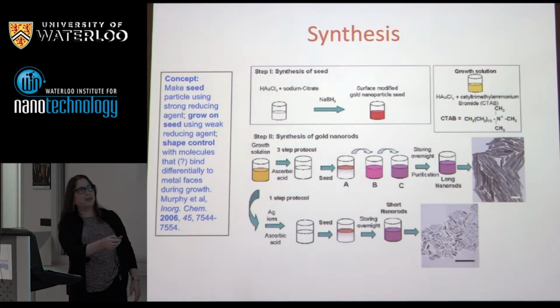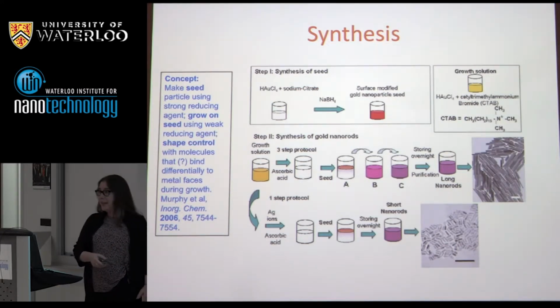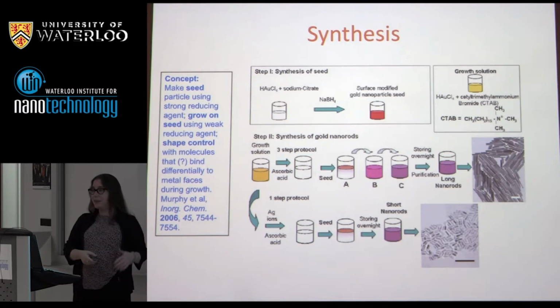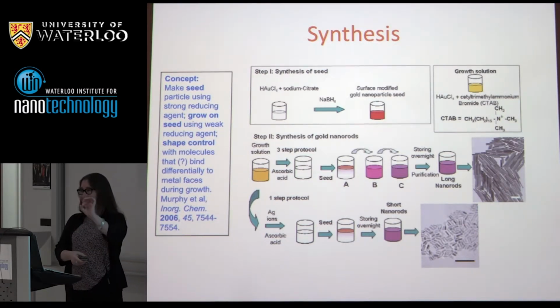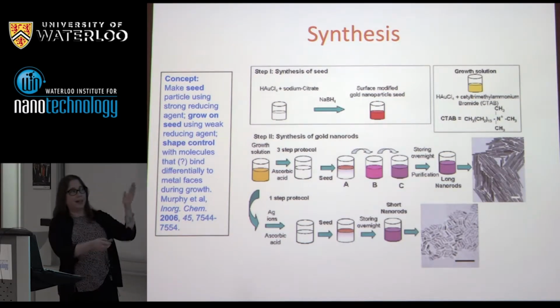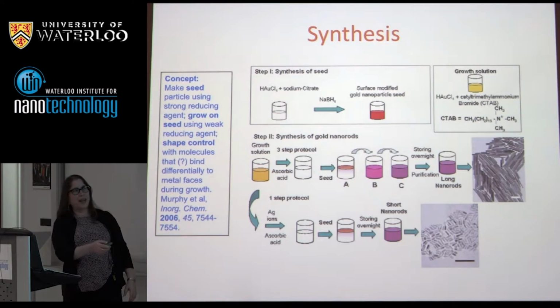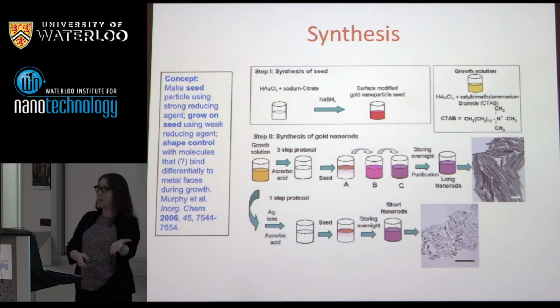And then we're going to come in with a strong reducing agent, sodium borohydride. The idea is that you're going to quantitatively convert all your gold-3 ions into gold-0 atoms that are going to form these little seeds, these little tiny particles. And indeed, that's what happens in about 30 minutes, and you get these solutions that are kind of reddish-brown, and they don't actually show a nice plasmon band because these particles are too small to show a plasmon.